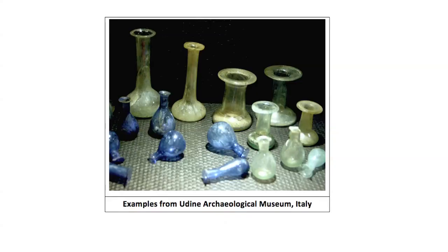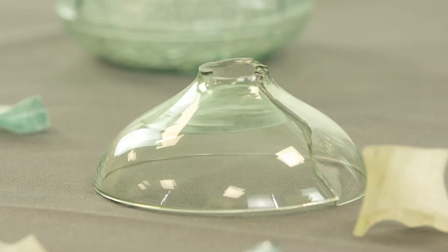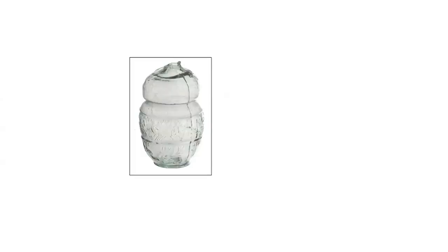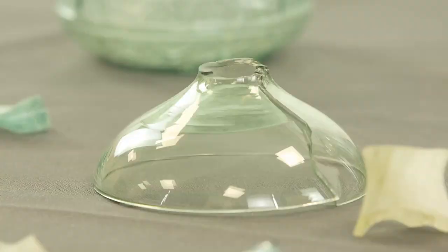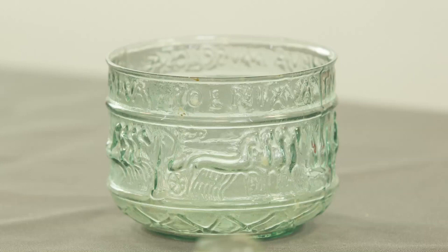Most of the moils from London are cylindrical, produced in the manufacture of narrow-necked vessels such as flasks and jugs, or open vessels with folded rims. But wider lid moils, found at Basinghall Street in colourless glass, come from vessels with wide mouths and cracked-off rims, such as cups and beakers. The lid moil was removed from the vessel when cold. The illustration shows a replica cup made by David Hill and Mark Taylor with its lid moil attached, and another with the moil removed. Such decorated vessels were blown into moulds, as this example of a similar vessel from Cologne shows, and this replica sports cup showing a chariot race.